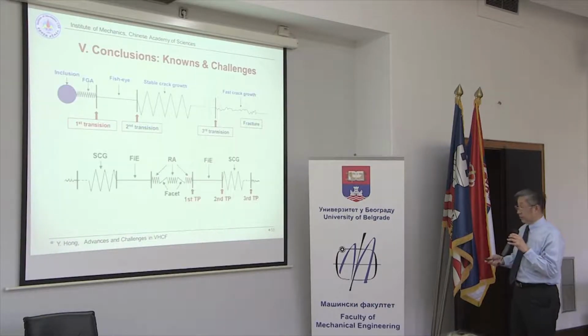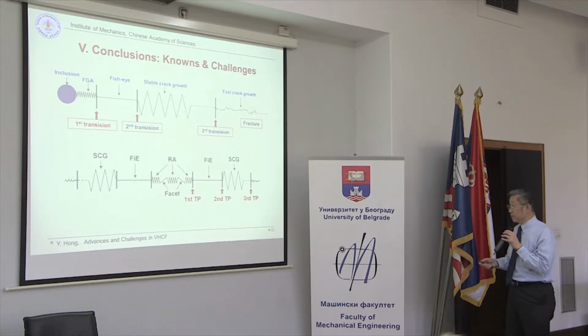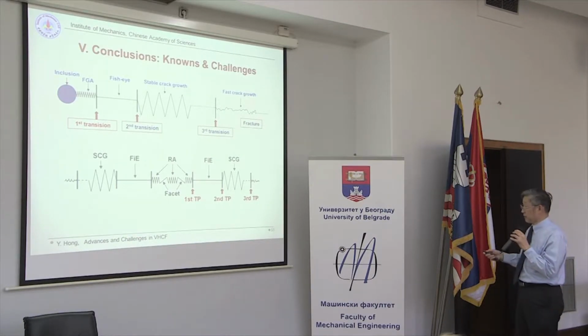I think I would show you the two schematics of this process. The first one is for high strength steel, initiation from an inclusion, and it's an initiation region of FGA, and we said it's the first transition. And this part is so important that it consumes more than 95% of the total fatigue life. So we should pay more attention to this part.